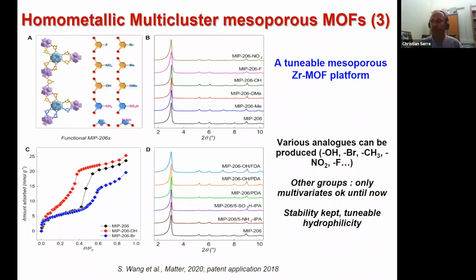Another interesting feature of these phases is that the functional group, in the 5th position of the isophthalic benzene ring, points at the center of the mesopores. And you can see that we could obtain by direct synthesis a lot of variants of functionalized isophthalic groups that are all commercially available. And only in a few cases, we could not obtain the pure MOF by direct synthesis, for some unknown reasons.